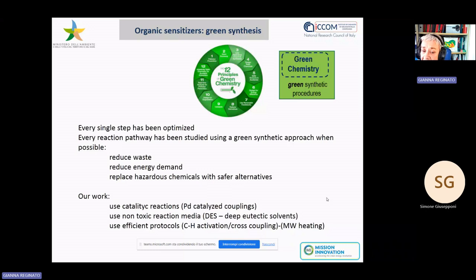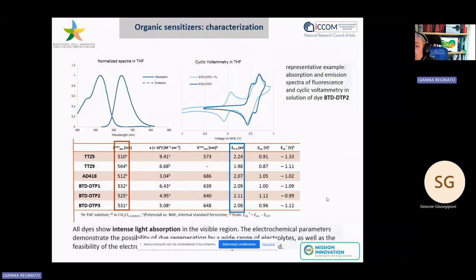In fact, for example, for some of these molecules we have prepared, we have been able to optimize the process using non-toxic reaction media and using very efficient protocols, like substituting the cross-coupling reactions we use normally, which are metal dependent, palladium catalyzed, with the processes of CH activation, again palladium catalyzed, but with a big reduction of waste. I don't go into details here, but I am ready to do it if someone is interested to go more in depth.